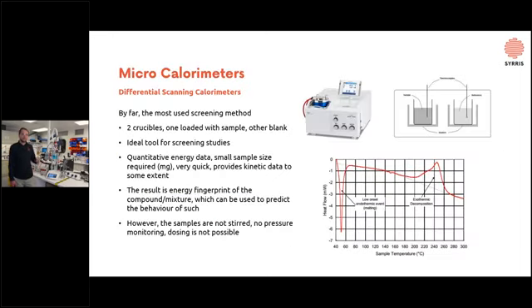So the first group, the microcalorimeters or differential scanning calorimeters, are very simple devices. We have two crucibles, one loaded with sample, the other one blank, and basically we will heat up both crucibles linearly and measure the heat generated inside of the crucibles. And it's differential because we are actually comparing the blank one with the sample one. It's an ideal tool for preliminary screening studies because we require a very small amount of sample, usually micrograms. The experiments are very fast, and what data can it give us? It's usually quantitative energy data. With a small sample, it's very quick to perform, and we can get information that lets us predict the behavior of compounds and mixtures at higher temperatures.